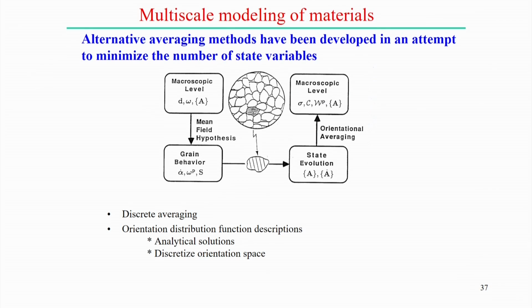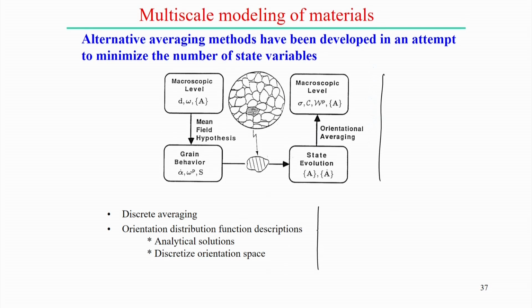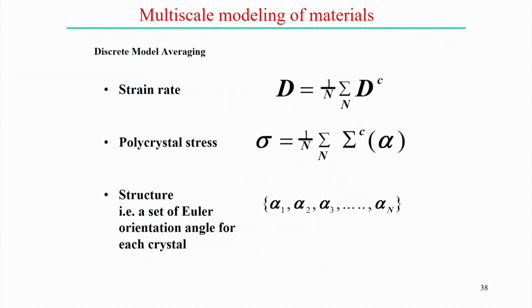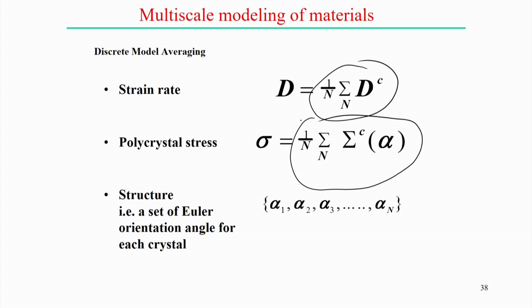Similarly, alternative averaging methods have also been developed in an attempt to minimize the number of state variables. That is another important issue in the microscopic model: if it is possible to reduce the internal state variables, that can be done through some discrete averaging of certain properties. We can derive orientation distribution functions based on an analytical solution or a discrete distribution space. It is possible to reduce the number of state variables in the microscopic model. In the discrete model, we average the strain rate and the polycrystal stress, and the structure is a set of Euler orientation angles of each crystal. These are the typical discrete model averaging of all the state variables or properties.